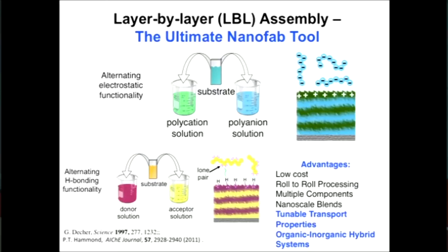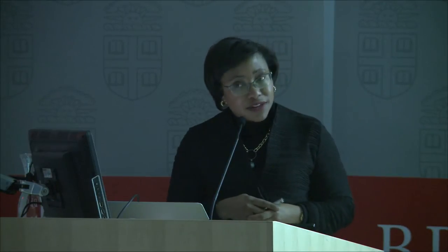So why is this interesting for drug delivery? It turns out that you can incorporate anything that is compatible in water. There are a range of drugs that are nucleic acids or proteins that are very sensitive to processing with polymers, with solvents, and with temperature, but you can deposit them in water and adsorb them in their most active form. And this allows us to get a very active form of a biologic drug into a very thin film.